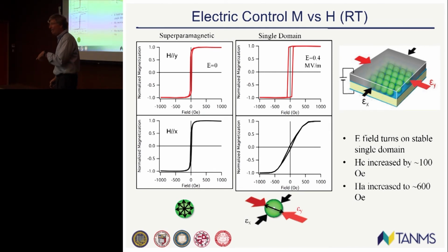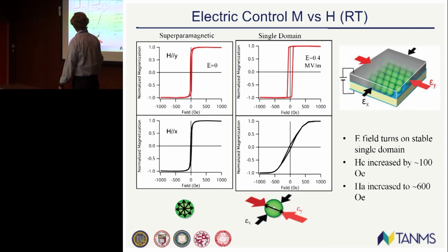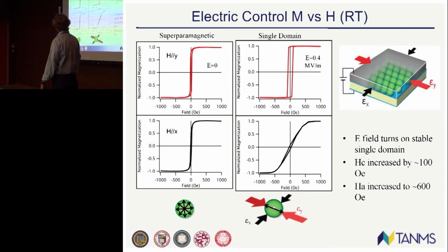Now let's take that same sample and apply an electric field, which applies a strain, and let's repeat these MH curves. So we apply an electric field of about 0.4 megavolts per meter, and notice the y-axis suddenly turns into a really nice easy axis. The black axis, or x-axis, suddenly turns into a hard axis. So what we've done, we believe here, is popped it from a superparamagnetic state into a single domain ferromagnetic state.